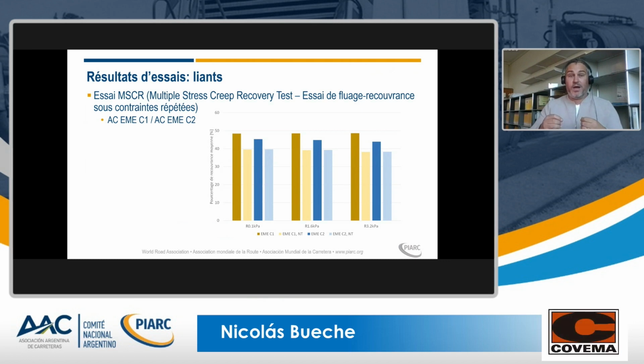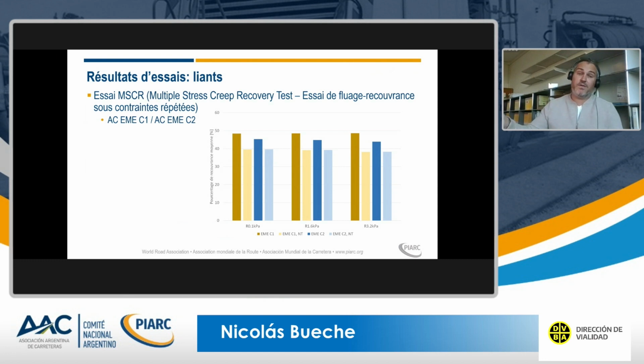Usually we always say that RAP is a hard binder. In the case of high modulus asphalt, we have to keep in mind that we work with a very hard binder, a 10/20 or 15/25. This means the binder coming from the RAP is a high penetration binder, so a softer binder, in the case of high modulus asphalt, while usually we always say the binder coming from the RAP is a hard binder. This is maybe just valid for the Swiss scale. In our country, most of the reclaimed asphalt pavement will have a penetration between, I would say, 22 and 30.